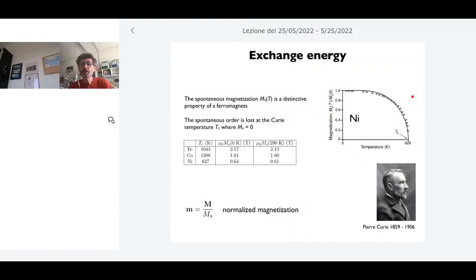How can a ferromagnet be not magnetized? How is it possible to take a piece of iron and find it not magnetized? Well, it's possible because this means that you will have regions where magnetization is pointing in one direction and a region pointing in another one. Otherwise, you would not explain why it's zero. That's the enormous difference between ferromagnets and paramagnets.